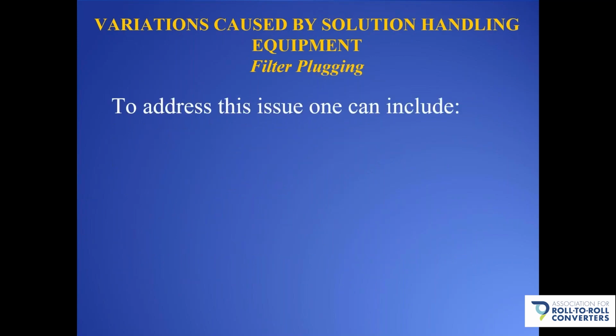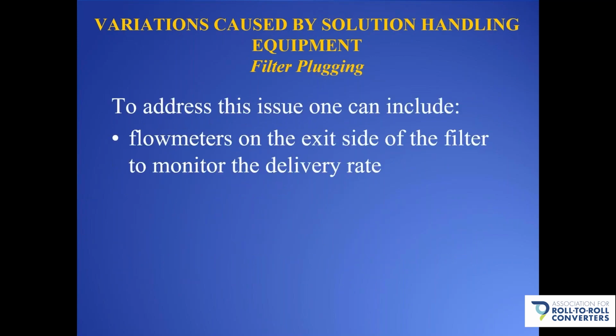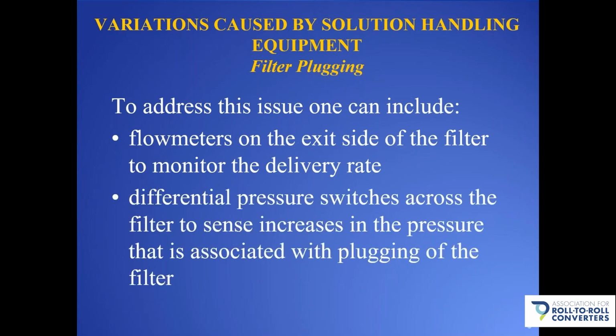So how do we address this issue? Well, we can put a flow meter on the exit side of the filter to monitor the delivery rate and even use that to control the pump again. Or we can use differential pressure switches across the filter, where these switches tend to sense the increase in pressure that's associated with the plugging of the filter and therefore notify you that there is indeed an issue with the filter plugging.